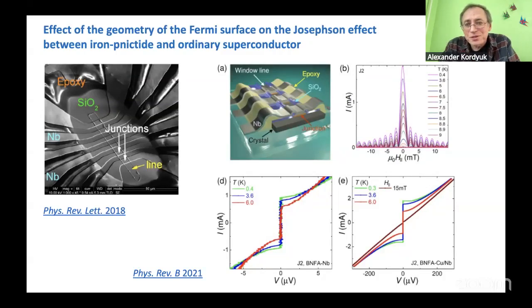We were the first in the world to succeed in making a good Josephson junction between an iron-based superconductor and a traditional superconductor, in this case niobium. I expected that this experiment would prove that iron-based superconductors have no sign change of the superconducting order parameter, as is believed. But this experiment disproved my idea, because we see that the ratio IcRn, which should be proportional to the superconducting gap, was much smaller than would be expected for an isotropic superconductor.